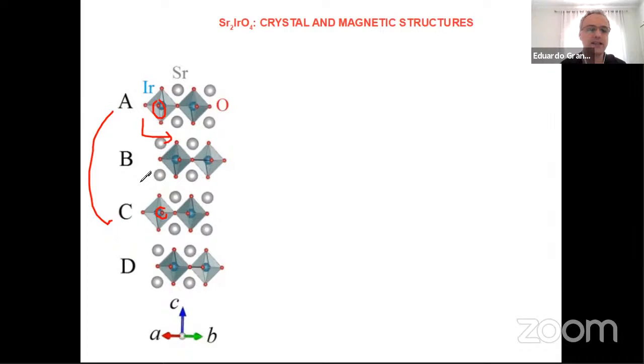So that kind of defines the crystal structure of the iridates, which is actually very similar to the crystal structure of the cuprates, which are a very important system of materials in condensed matter physics, because they generate high TC superconductivity. So one of the reasons why many people are interested in this kind of system is that the level scheme that I showed you in the previous slide leads to one electron in a twofold degenerate level, which is split by correlation. So that's pretty much similar to the level scheme of the cuprates. And there are predictions that these iridates also should show superconductivity because of the same physical ingredients as the cuprates. And there is a long story in that direction that I don't want to go into, because our results are something different, but that explains a lot of why so many people are looking at the iridates